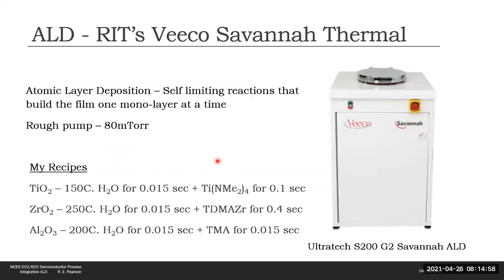Atomic layer deposition was used to put down the oxide layers as it is more accurate at the nanometer level and also gives a purer composition compared to CVD deposited films. This is because it involves a series of self-limiting reactions that deposit the film one atomic layer at a time. As part of the reactions, all three films had deionized water pulsed in for 0.015 seconds, followed by the respective precursors.